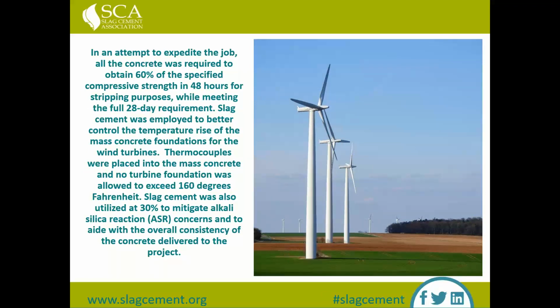They wanted to expedite the process on this job, so the concrete was actually required to obtain 60% of compressive strength in 48 hours for stripping purposes, and still had to meet the 28-day requirement. There were some design challenges within that because of the typically lower early strengths on the slag, but in this case they were able to affect that change within the design structure and hit those requirements.